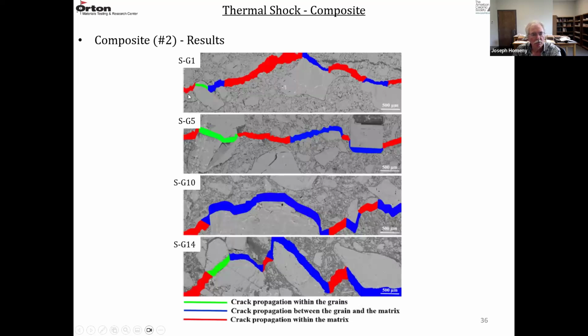So this is SG1, SG5, SG10, and SG14. And you can sort of see from these diagrams that the crack path is more tortuous in the SG14 structure. So if it's green, you can see it's propagating across an MgO grain. If it's blue, it's the interface between the MgO grain and the matrix. And then if it's red, it's through the matrix.